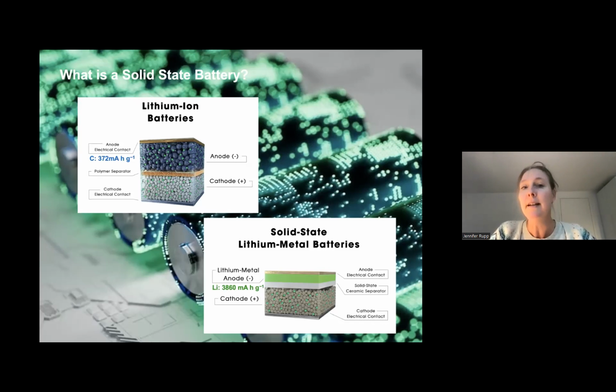So what is a solid-state battery? When you consider a classic lithium-ion battery, like in this phone, you have an electrochemical cell with two electrodes, cathode and anode. In the middle, you have a polymer separator and some organic liquids that are the effective electrolyte of the cell. Because of that setup, you're bound to certain materials, for instance graphite for the anode, which gives you a cap on how much lithium you can store, somewhere around 370 milliamp hours per gram.